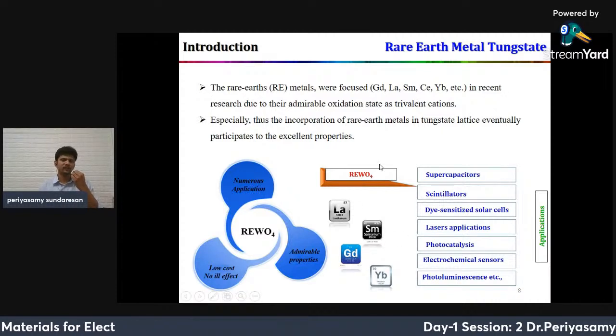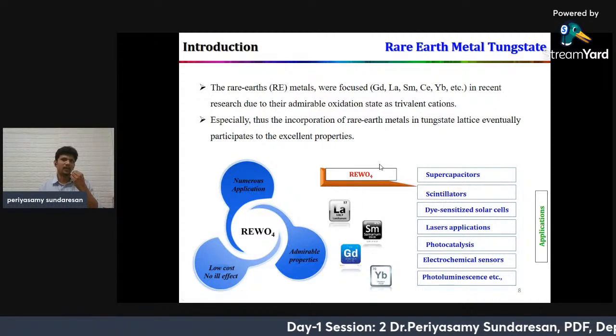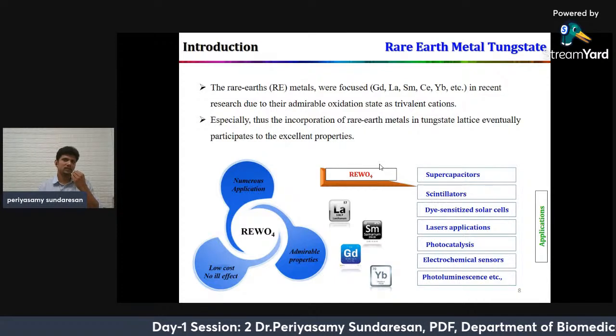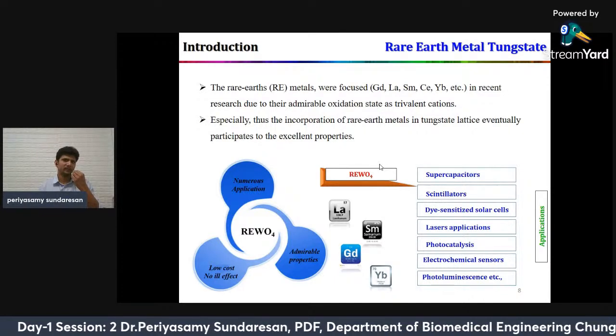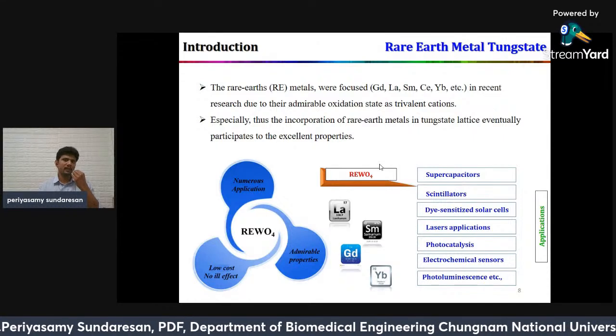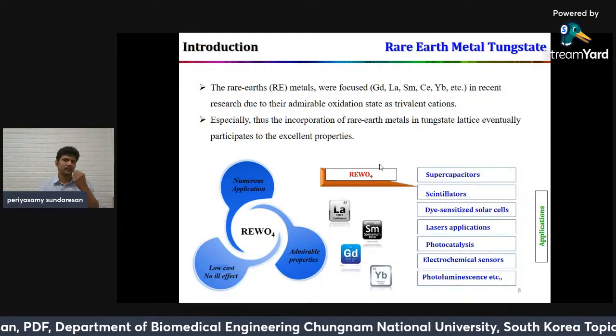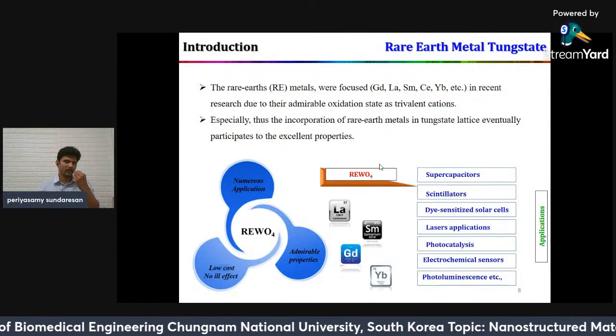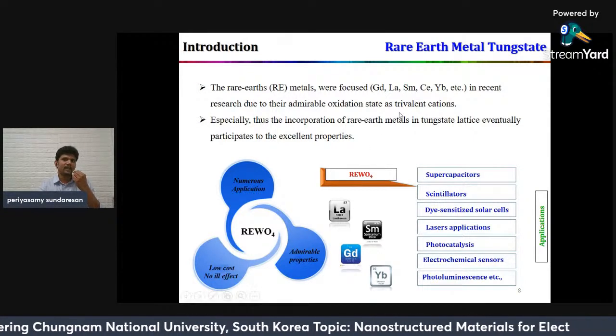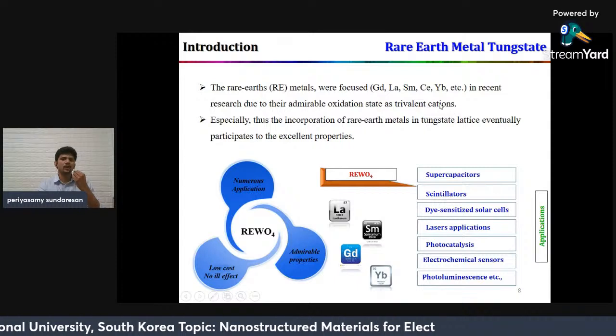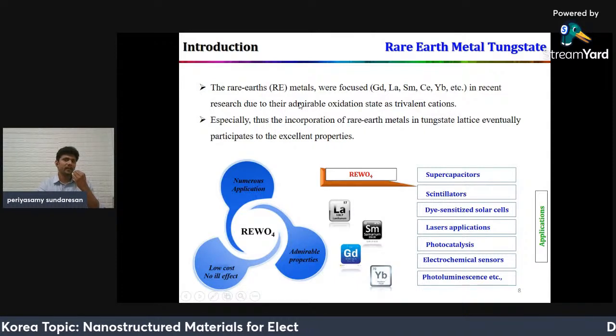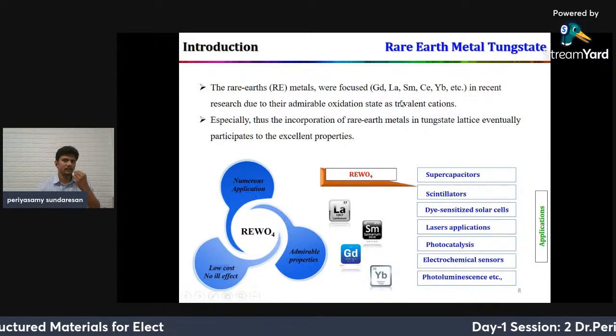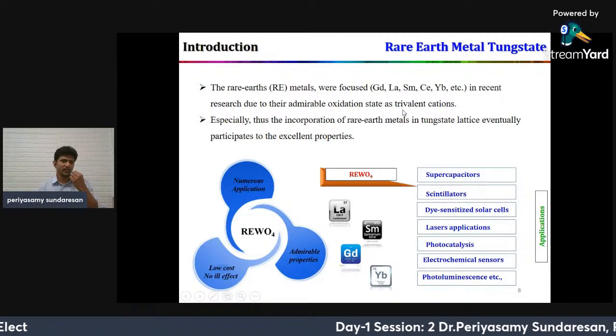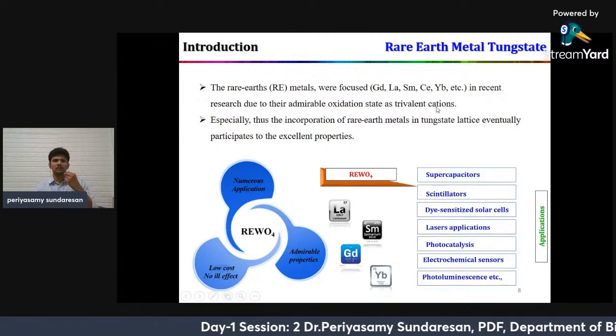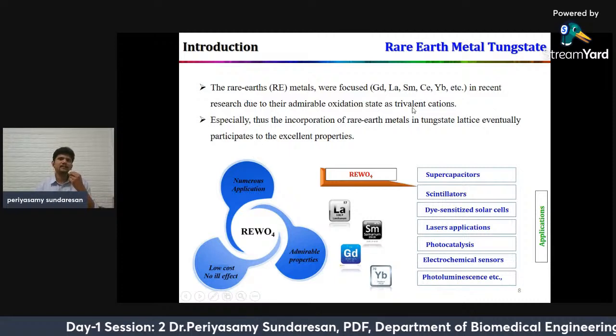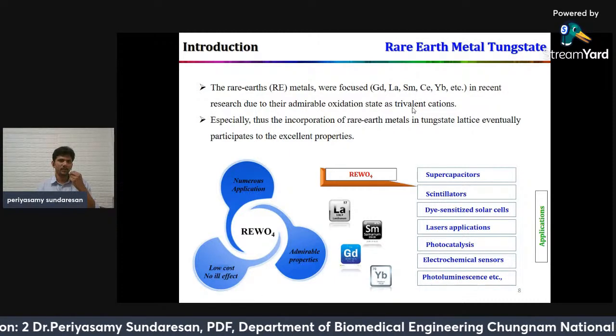The shielding effect means the core shell s orbitals are pulling the electrons towards the nucleus. That's why the atom size decreases, so we get a more active area. It means more orbital vacancies, so that we get trivalent cations. Compared to the S block elements, where we get only divalent cations, with the rare earth elements we can get trivalent cations. So that's why I focused on the rare earth oriented metal tungstate for my application work.